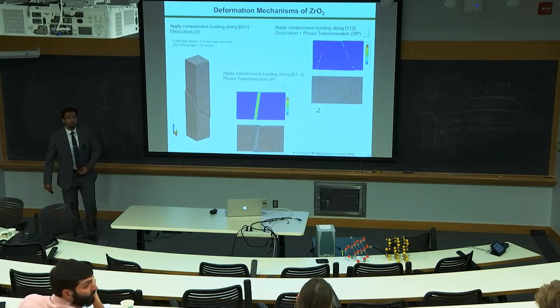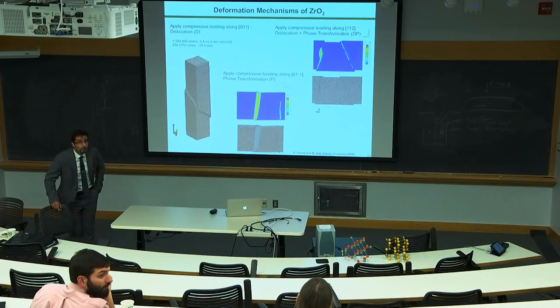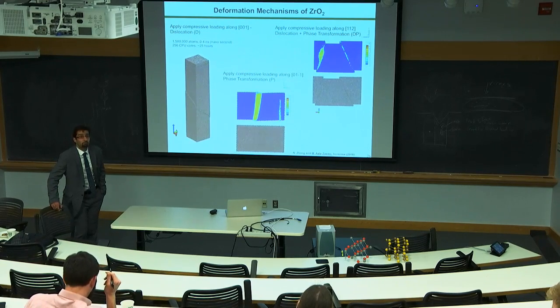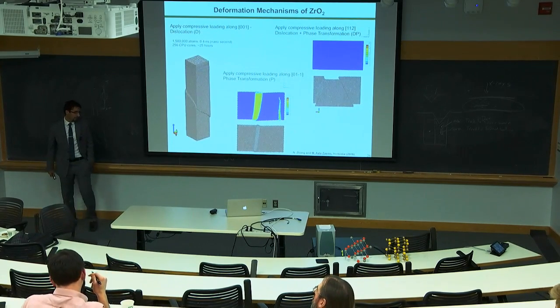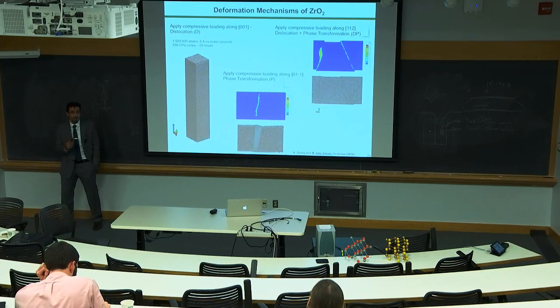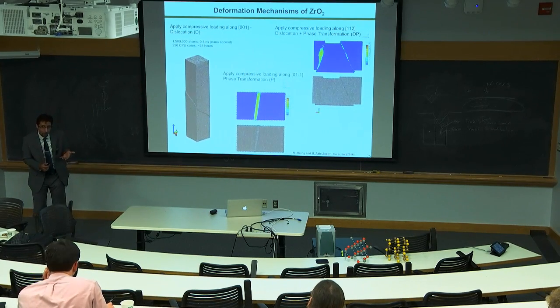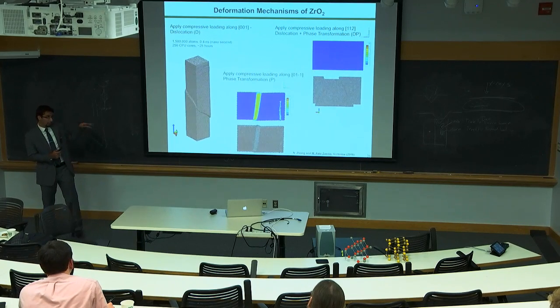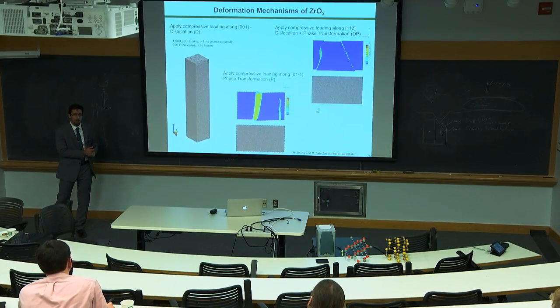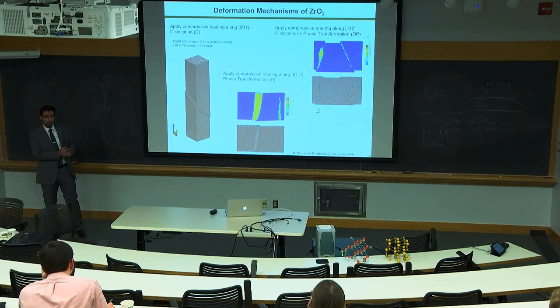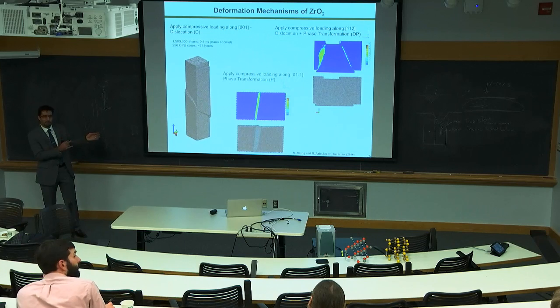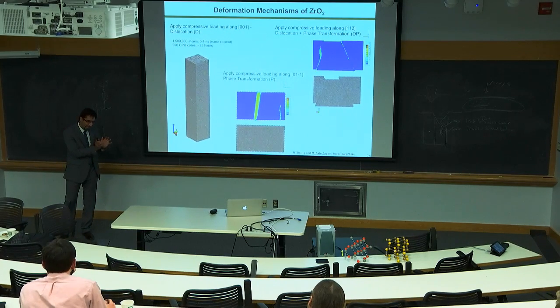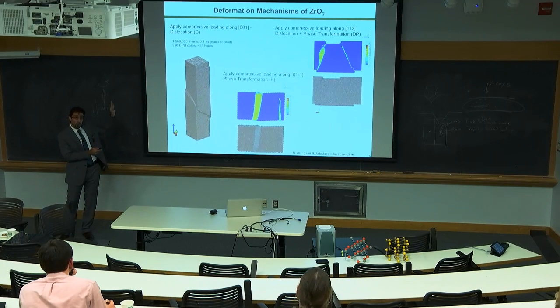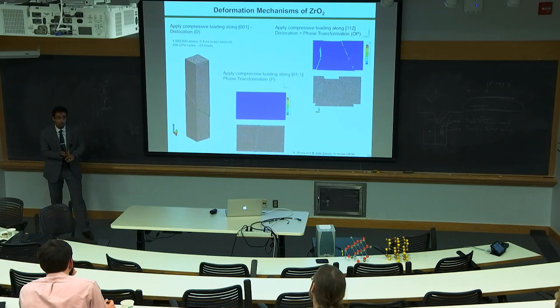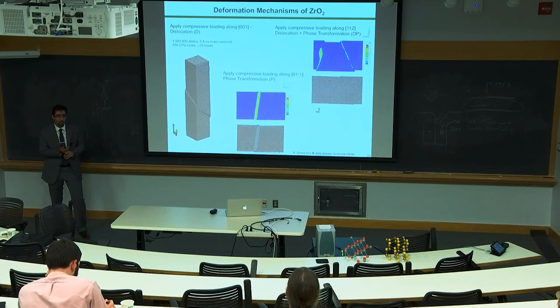Have you also looked into nucleation before applying the basic model? Very important, especially for solidification and crystallization. It's very important to have a really good nucleation criterion. Right now we are looking at a couple of alloys, aluminum-copper and magnesium-aluminum, especially these two because of the funding we have. We're at the earliest stage of solidification, looking at nucleation. But for those I showed you, those are thermal-fluctuation nucleation based on classical nucleation theory.